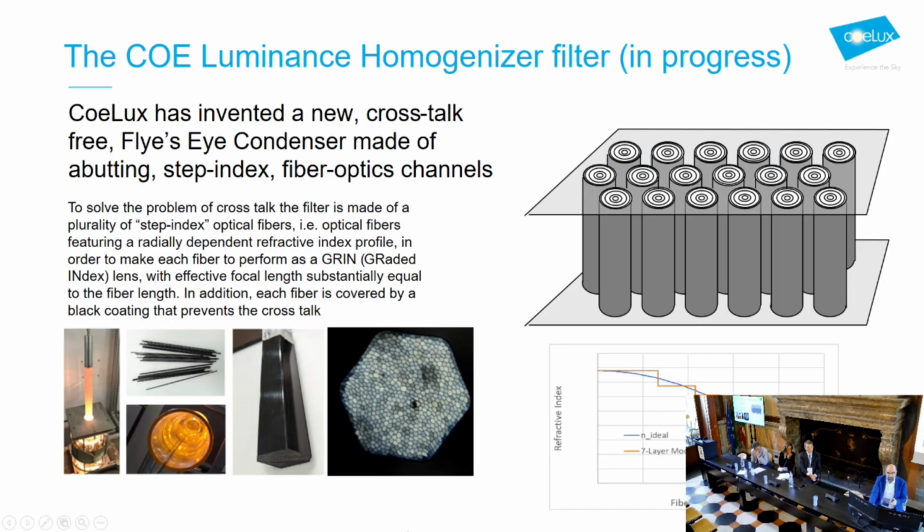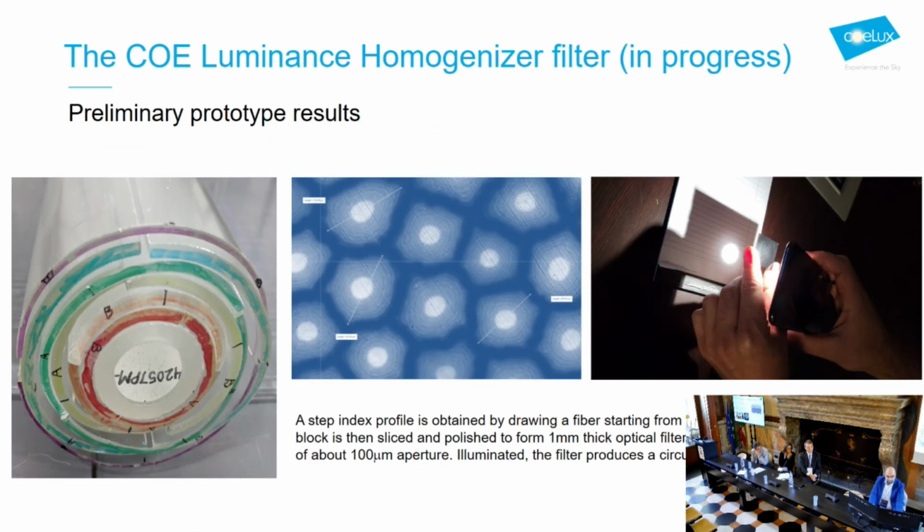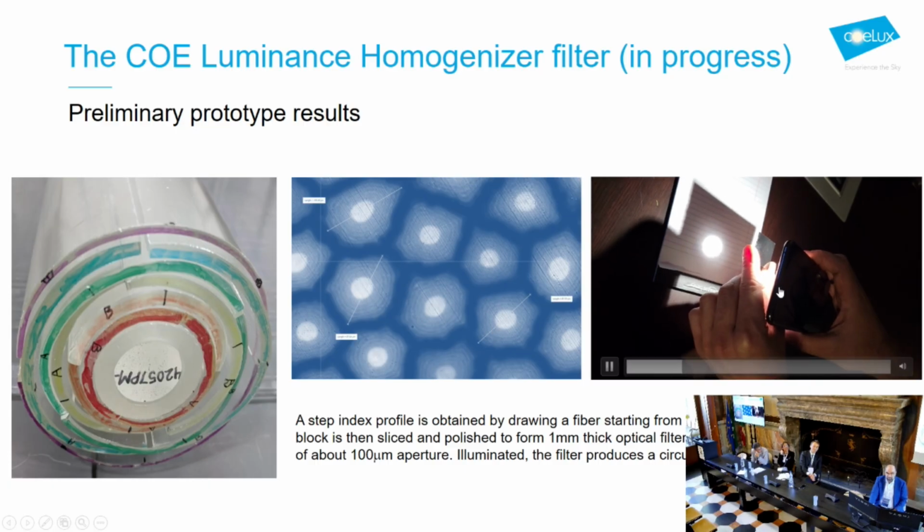So what we did is take this cylinder made like a matryoshka of different polymers with different index, and do this process, like making the tagliatelle, so many times. Finally, you end up with the filter, and you can see here inscribed all this structure of different index material on every 100 micron. And this effect is incredible.